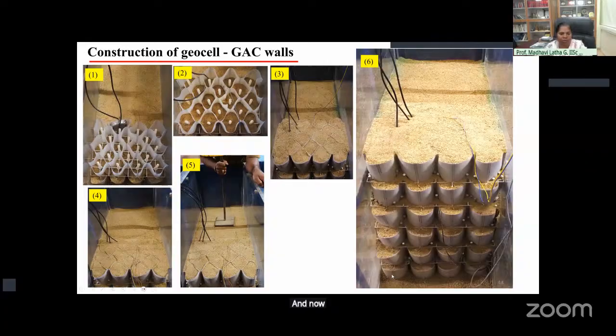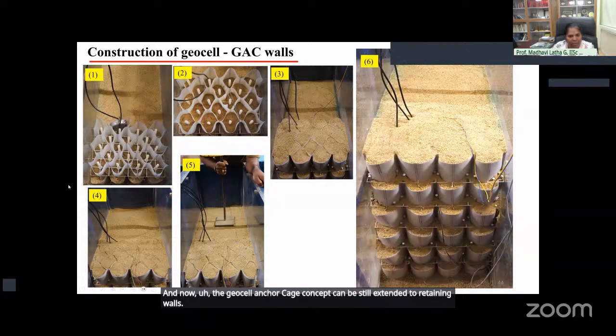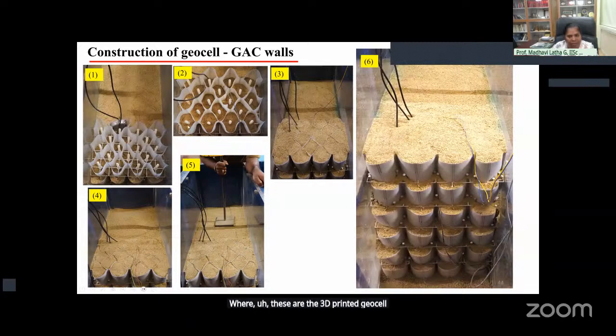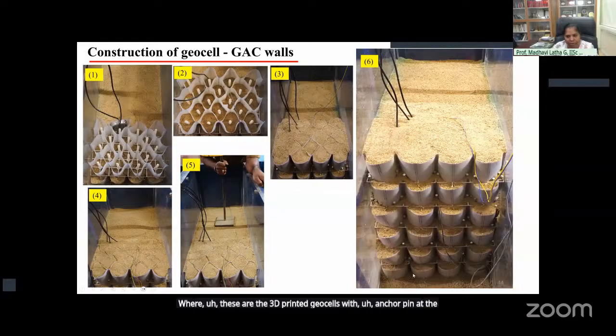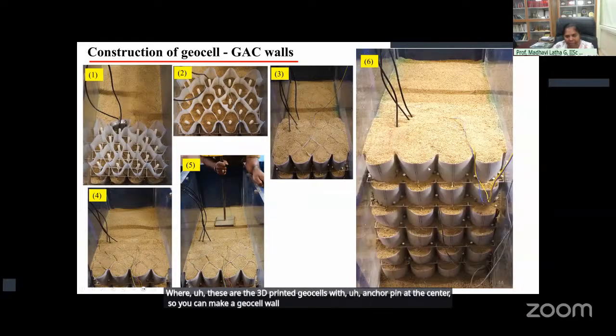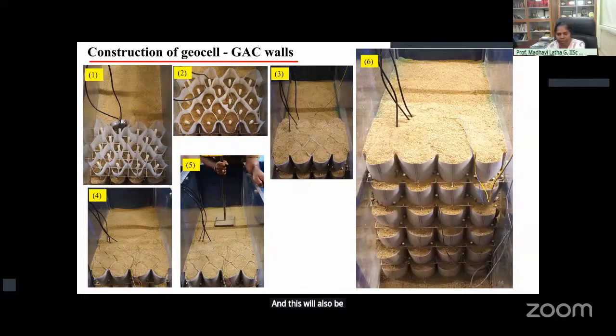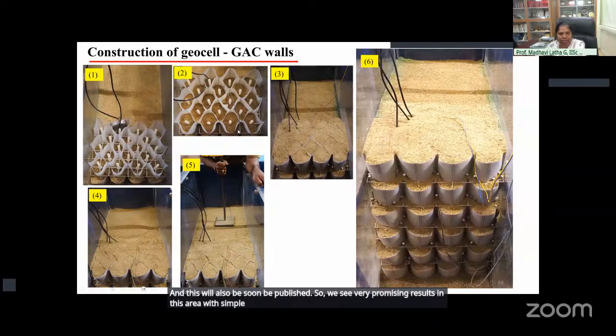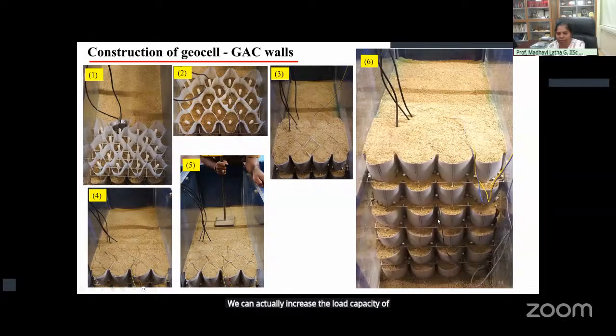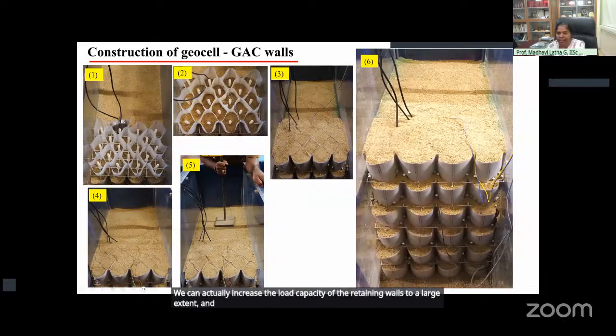And now the geocell anchor cage concept can be extended to retaining walls, where these are the 3D printed geocells with an anchor pin at the center. So you can make a geocell wall and test it under static and seismic loading conditions. This is ongoing PhD work by my student Arya Krishna, and this will also soon be published. So we see very promising results in this area. With a simple intervention in the form of a geocell anchor cage, we can actually increase the load capacity of the retaining walls to a large extent, and also completely restrict the horizontal movements of these walls.